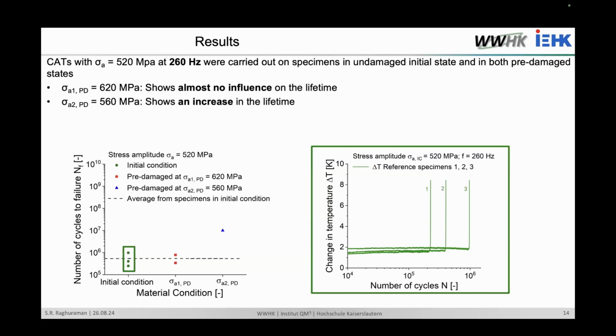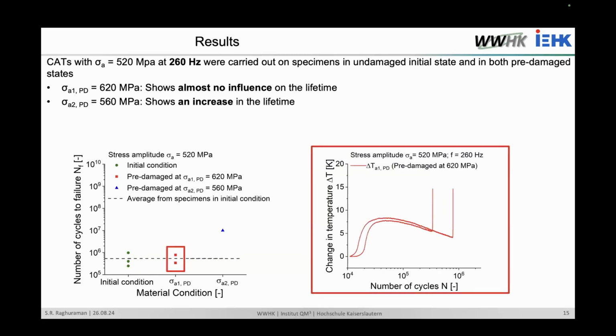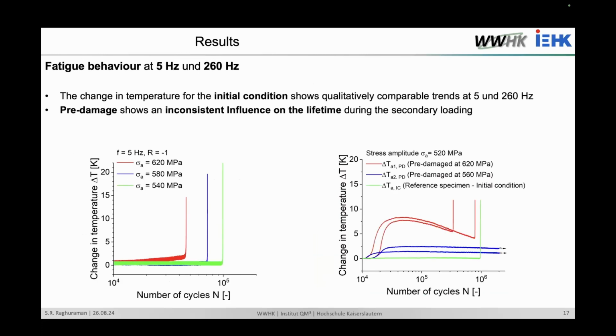We can also note that the 620 megapascal pre-damage has almost no considerable, no clear influence on the lifetime, but the 560 megapascal pre-damaged specimens actually exhibit an increase in lifetime. These are the cyclic deformation curves for the second condition, and this is for the last condition, at 560 megapascals. We also tried to compare the difference between the experiments at 5 hertz and 260 hertz. This is not a direct comparison, just for representation. You can see that the initial condition specimens have a very comparable output, and the specimens at 620 megapascals show a different trend, as do these with the blue lines, which are preloaded at 560 megapascals.